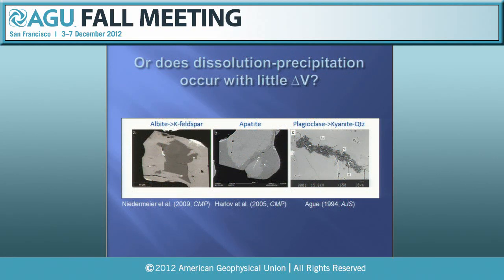Maybe it's a dissolution precipitation type reaction. And this has been shown experimentally and in the field too, but the experiments are extraordinary, where you can see albite here in the core being replaced by K feldspar, replacement of apatite in these experiments. And this is a natural example, somewhat more complicated, of replacement along a fracture.